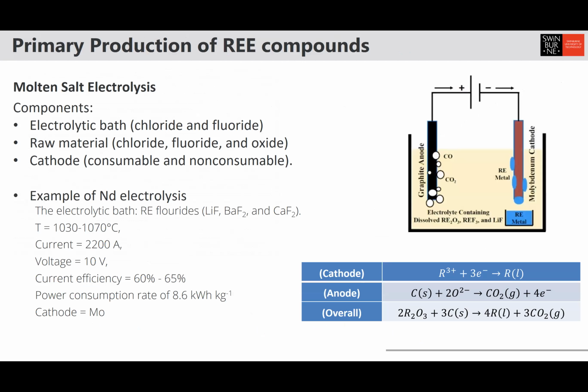Right, so we talk about molten salt electrolysis. As I mentioned earlier, in essence, we try to dissolve the different types of compounds, chlorides or fluorides, and oxide as well, into a salt bath, which is also made of chlorides and fluoride. The bath itself, we call it electrolytic bath, and we have the rare earth chloride and fluoride or oxide as the raw materials, and then we also have the cathode, right? We can have consumable cathode, anode, and we can also have non-consumable as well.